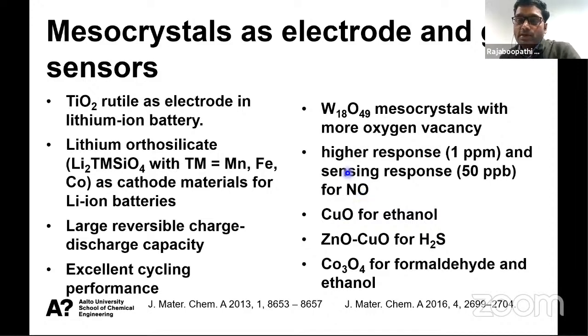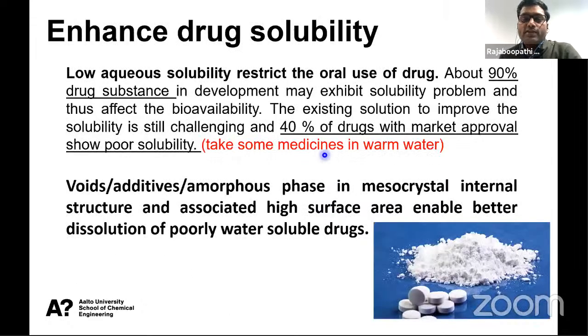So copper oxide can be used as mesocrystal to sense ethanol. Zinc oxide, copper oxide can be used for hydrogen sulfide. And cobalt oxide can be used as mesocrystal to sense formaldehyde and ethanol. So we can use sensors, and we can also use mesocrystal as the electrode in a battery and a supercapacitor. So here I'm using the mesocrystal strategy to enhance the dissolution of the drug.